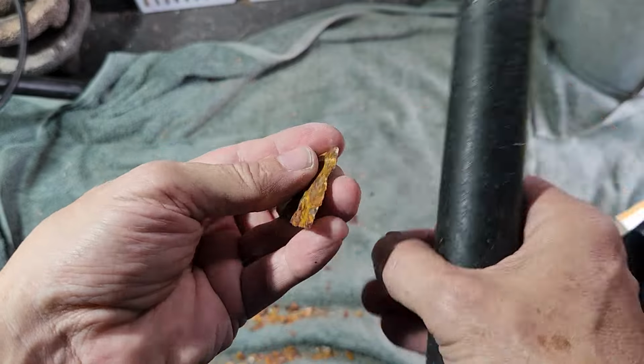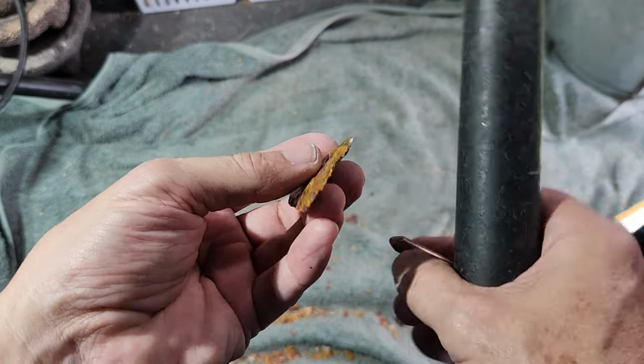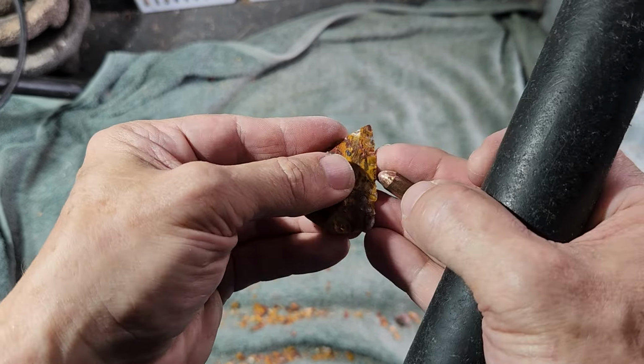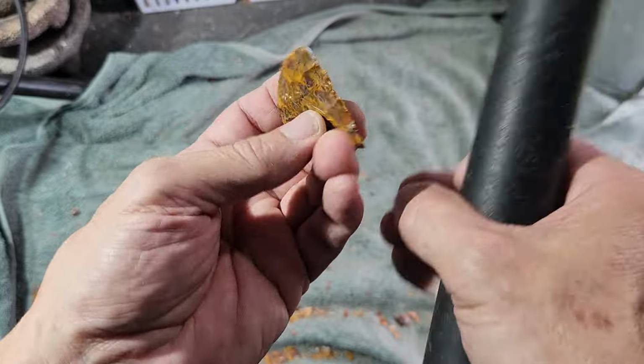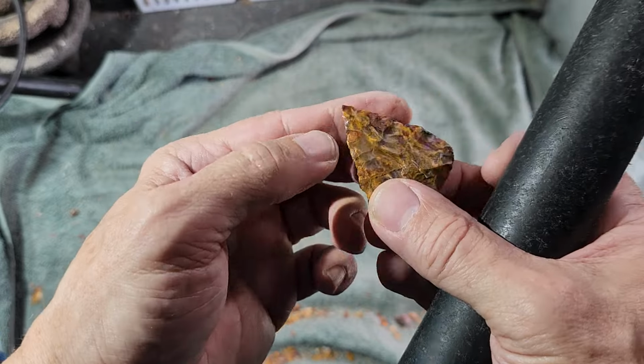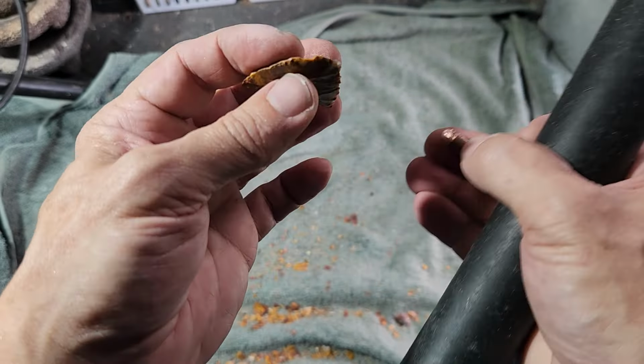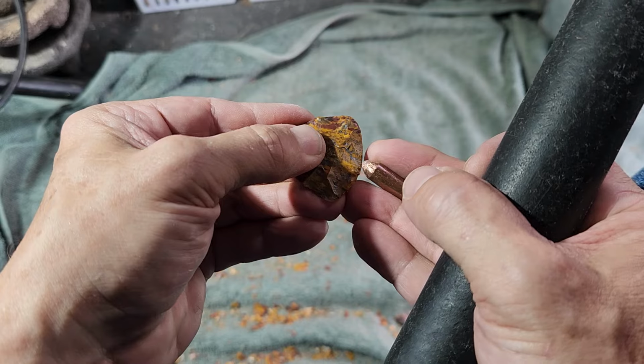Although both are important, you can heat rock up pretty fast and nothing will happen. But cooling it down too fast, for some reason, is more damaging. And you can heat the rock up and down, and do that cycle over and over again many times without harming the rock. I mean, it might get too fragile if you use too much heat, but it's not due to the number of times you use heat. It depends on the temperature. You can raise and lower the temperature on the rock as long as you do it slowly. Many times, and it won't harm the rock.